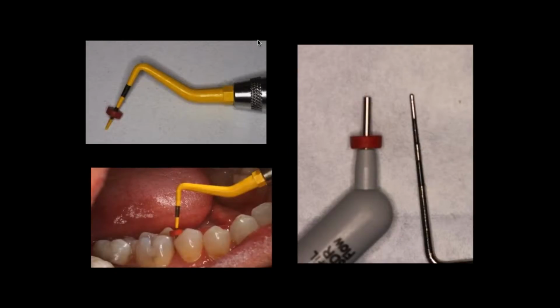Another trick I like to use a lot of times: we'll take a periodontal probe and measure the depth of that proximal box so that we know exactly how much bulk fill material we're able to place and to what depth. You can even use a little rubber gauge, an endo gauge, and place that on the tip of the bulk fill material syringe, unidose, so you know exactly the depth of placement. Because again, you don't want to violate that depth of cure rule.